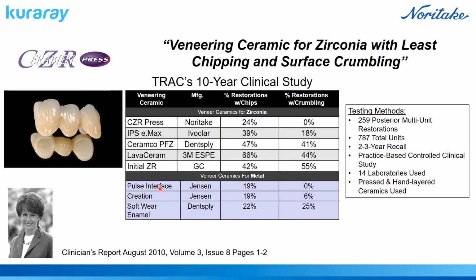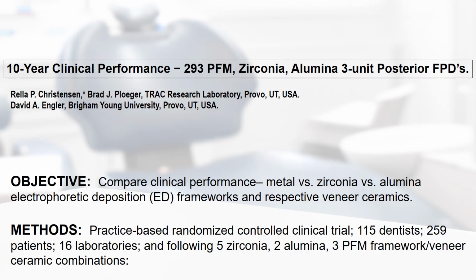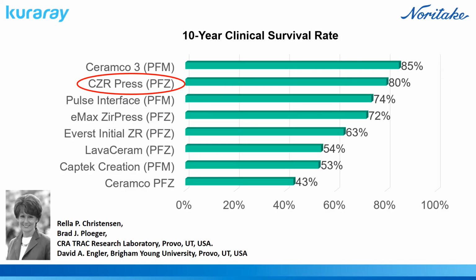19% cracking with the top PFMs, 24% with the CZR press. So you can do CZR press onto, or CZR layered onto a zirconia substructure if you have a clinical case that needs that. Okay? And this is the study. I'll just kind of breeze through it, but the survival rate was 80% with the CZR, and then Ceramco 3 was 85%. So you can see it's very high compared to even some PFMs. Okay? So you can see here some of them in the clinical study did okay, but the CZR press to zirconia substructures did exceptionally well. So you do have those options as well.